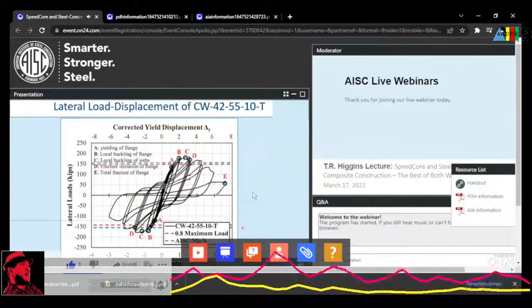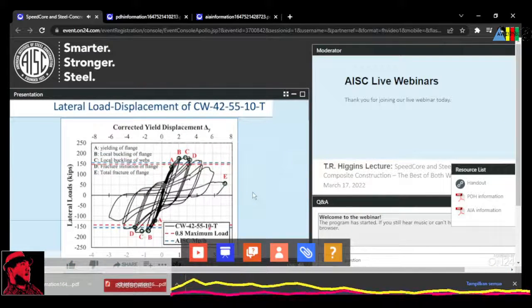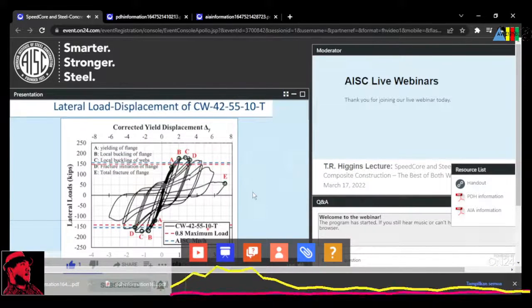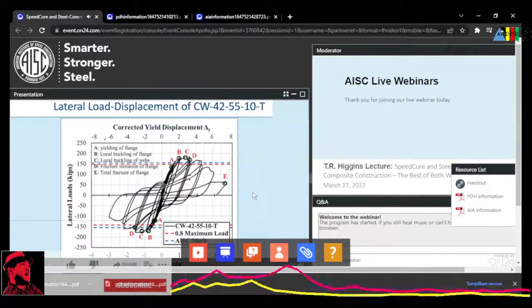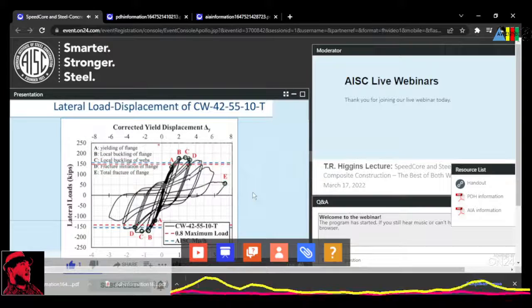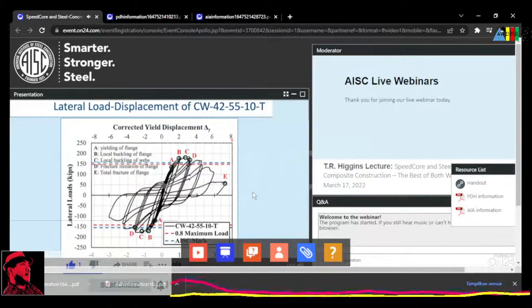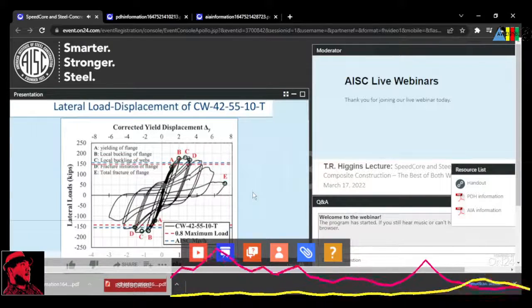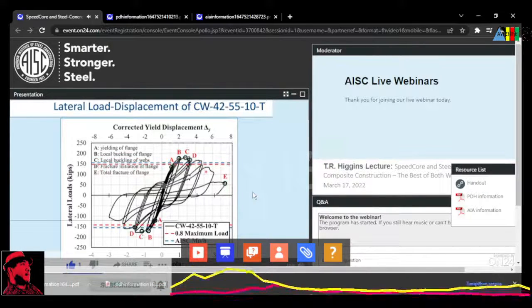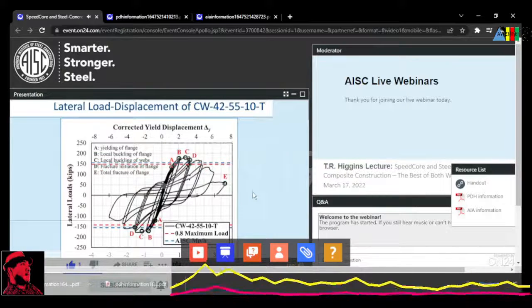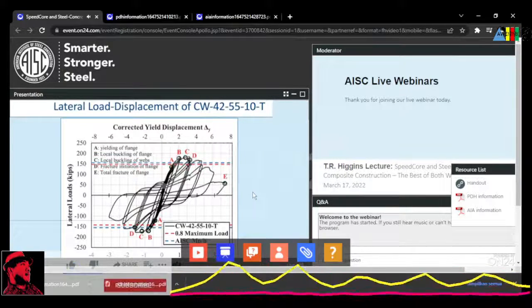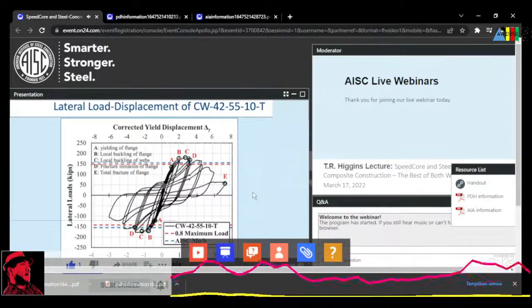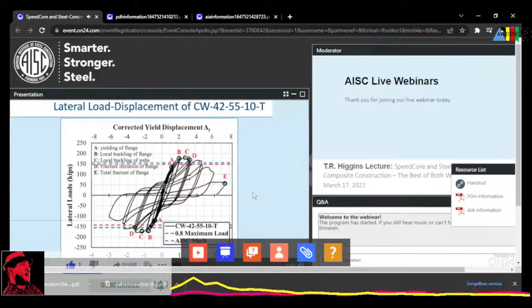Now, this is the cyclic lateral load displacement behavior of the specimen subjected to 10% axial load and with the tie spacing equal to wall thickness divided by 2. On the top, the x-axis is in terms of delta y or multiples of delta y. The occurrence of various events A through E are highlighted on the load displacement response. Event A corresponds to yielding, which occurs before event B, which is local buckling of the flanges. Event C corresponds to local buckling of the webs. D corresponds to initiation of fracture, and E corresponds to total fracture.